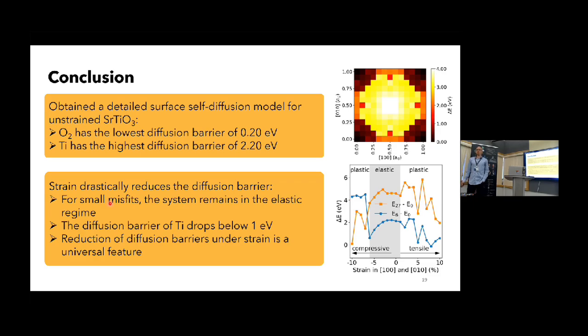How exactly do you differentiate between the strontium and titanium? Because it's a single atom layer. Yes, we will publish a paper on this, and I don't work with the system. It's basically a gold tip, which is activated with a red laser, and then with the near fields, you can measure one atomic layer.